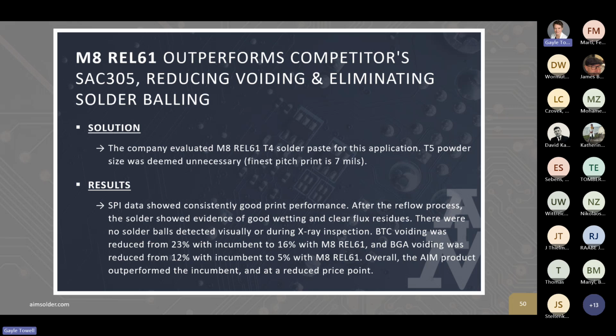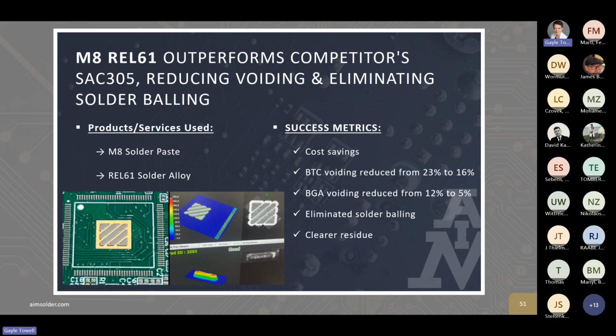And the end results were positive, good consistent print performance. After reflow, there was evidence of good wetting, flux residue was clear, and no solder balls were detected visually or on X-ray inspection. They also reduced their voiding on both BTC and BGA components. So they saved costs, reduced their voiding, the solder ball issue went away, nice clear residue from the M8 paste.